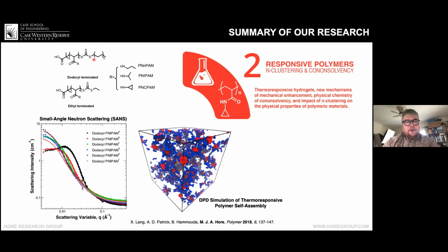So if it had, for example, 12 carbons on the end of the polymer, we noticed that it self-assembled into micelles, whereas with the shorter end group here, the ethyl group, it just existed as free polymers in solution. So certainly people had seen this before, but we were the first people to really look at this with neutron scattering. And what we found is that the transition temperature, where the polymer goes from a coil to a globule, really depended on how the polymer was assembled. So we matched up our neutron scattering measurements that we analyzed quantitatively with DPD simulations to see if we would get something reasonable and could understand it.